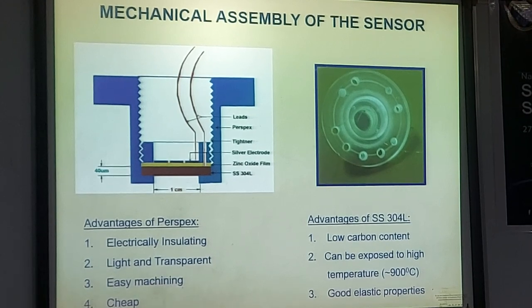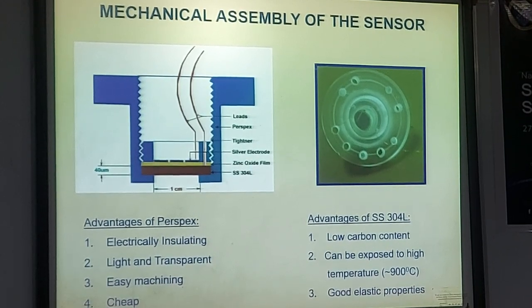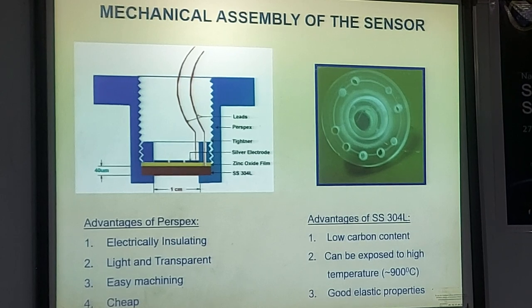And the diaphragm of this acoustic sensor is made of special quality stainless steel SS304L, which is a low carbon content material, can be exposed to high temperature up to about 900 degrees Celsius. And it has good elastic properties.